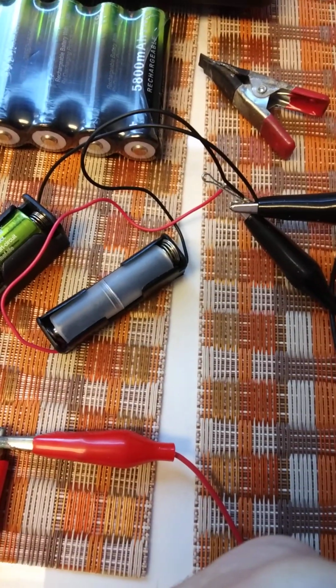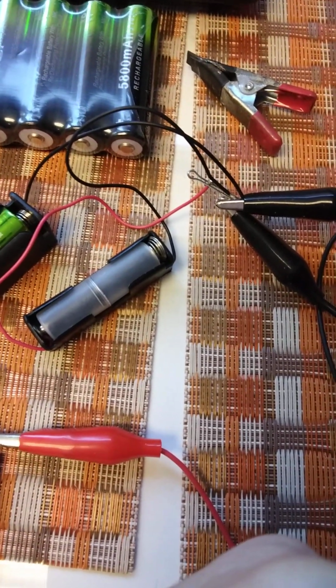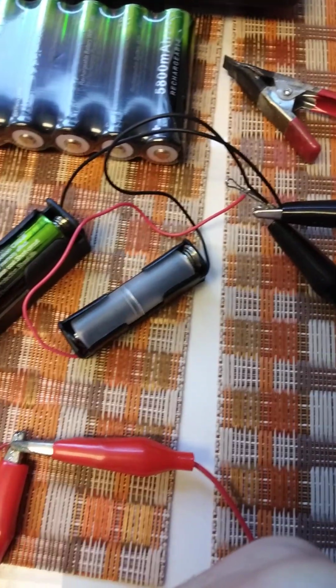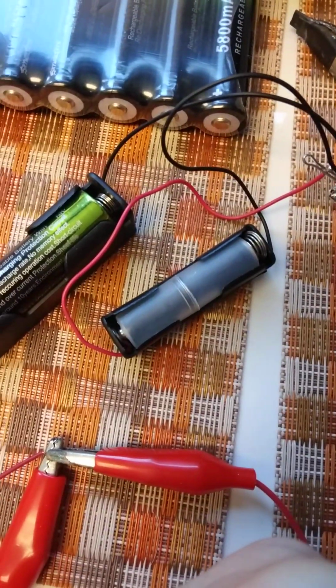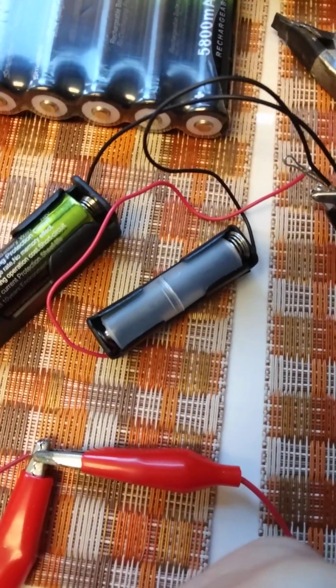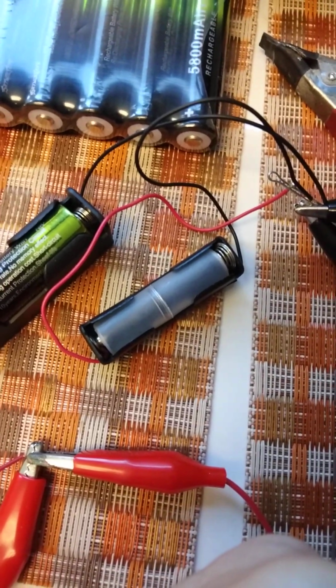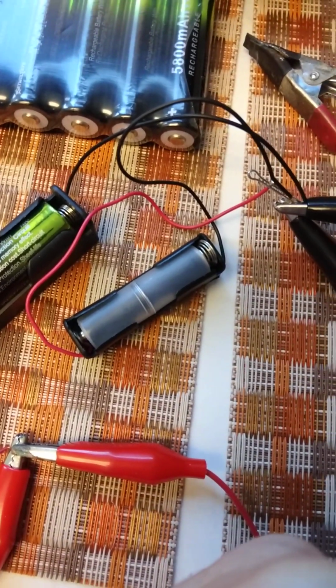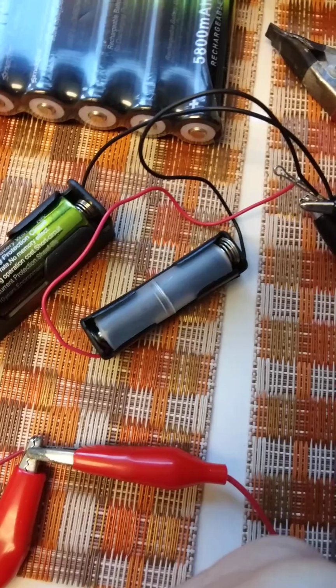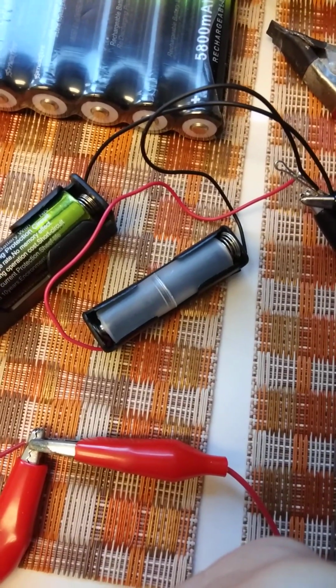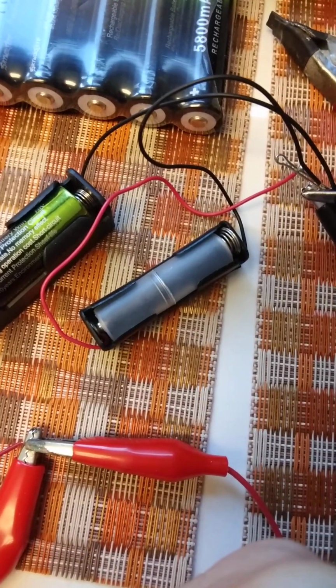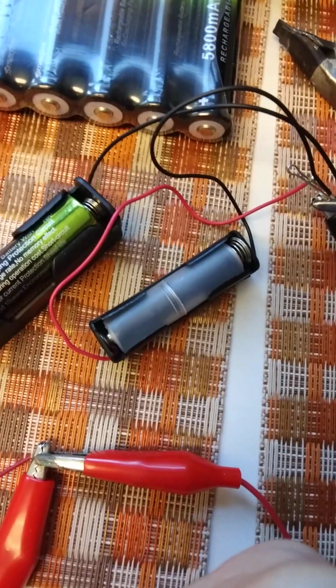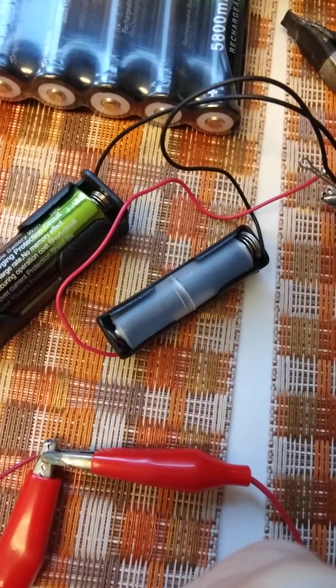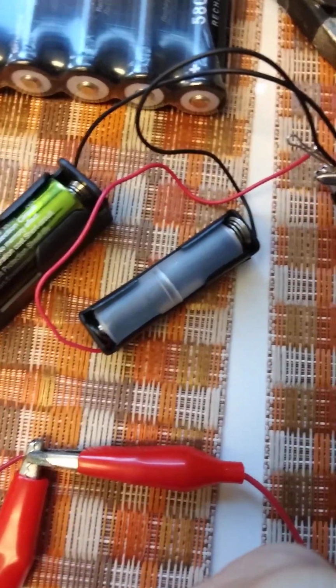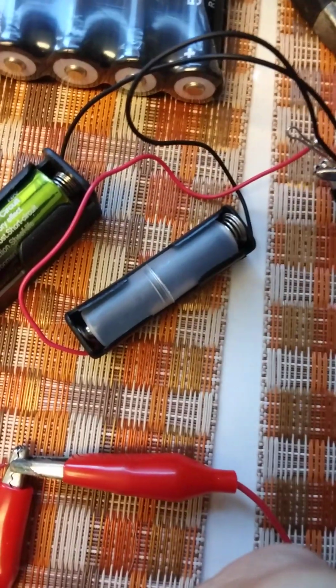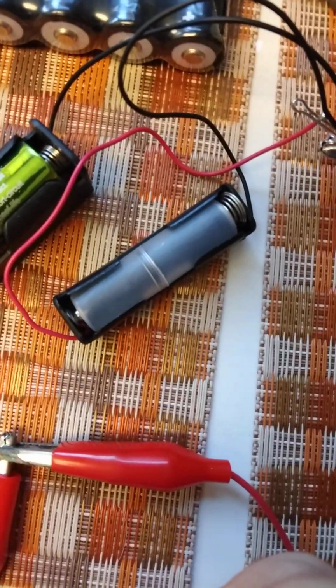Now, earlier today, I put it away already, I had run a graphite felt sample, dry, for 75 cycles, and the Coulombic ratio for capacity between charge and discharge was a beautiful ratio, just about 1.0. So I was able to do 75 runs with a packed graphite felt sample. And now, of course, we're doing the unraveled twine sample.